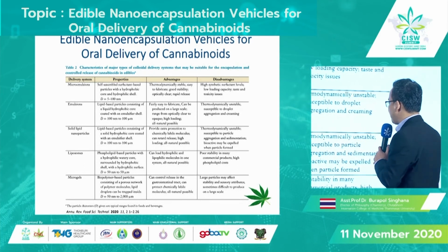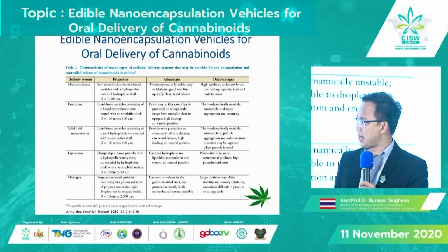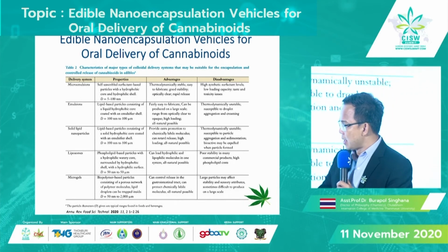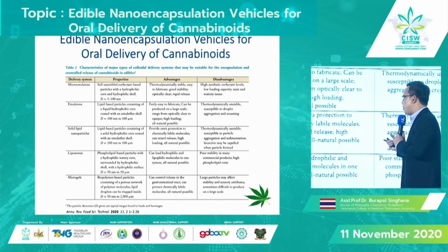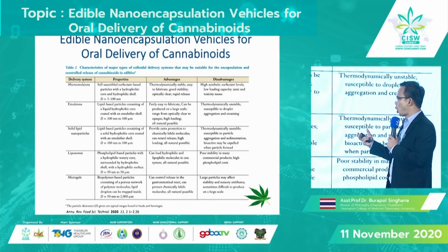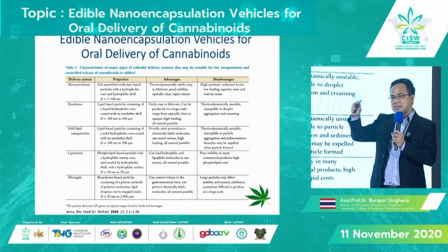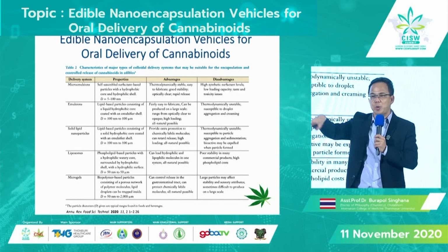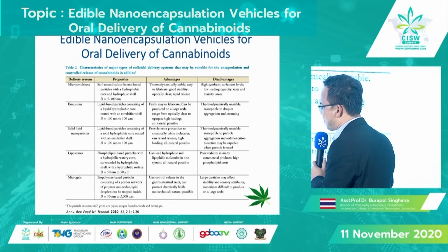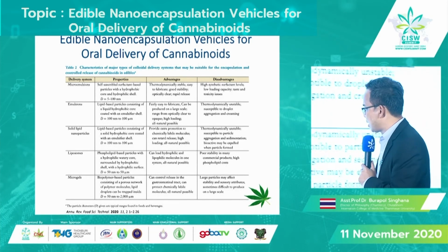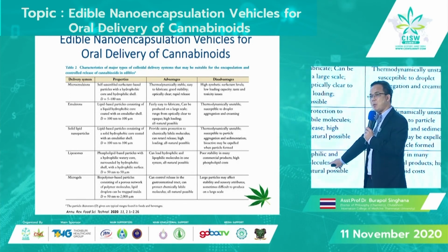Liposome is a common system used in pharmaceuticals and many other applications. Liposome is made from a phospholipid-based particle with a hydrophilic watery core surrounded by a hydrophobic shell. Inside is water-loving, and outside is coated with lipid-loving material. The size is about 50 nanometers to 50 microns. The good thing about liposome is that it can load both hydrophobic and hydrophilic molecules